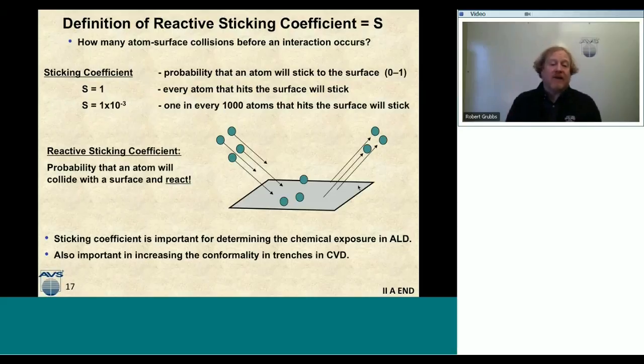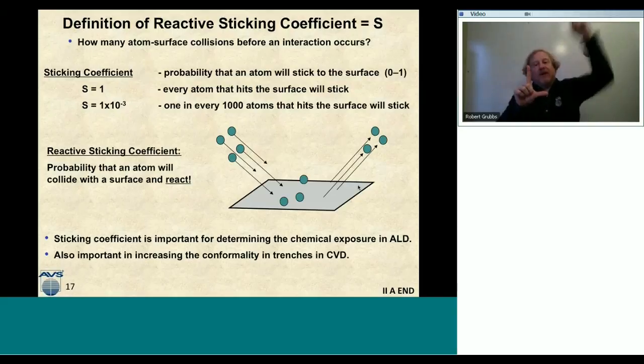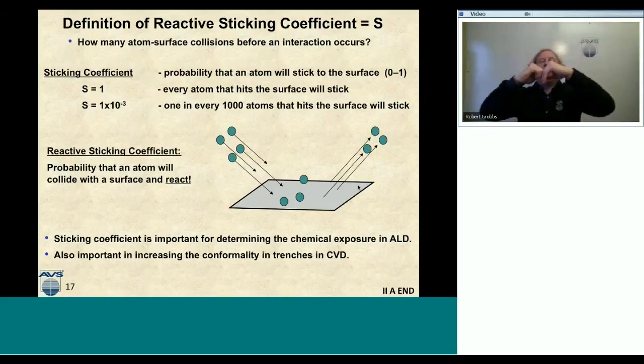The other thing I want to mention is that the reactive sticking coefficient is also important in increasing the step coverage inside a trench for chemical vapor deposition. And so if my reactive sticking coefficient is 1 or very, very high, and I'm trying to coat a trench, which I'm holding up my fingers, the molecules will come down and stick right on the edges of those trenches, and I'll get all of my deposition right on top of the trench and fall into this thing called bread loafing, or it'll pinch off.